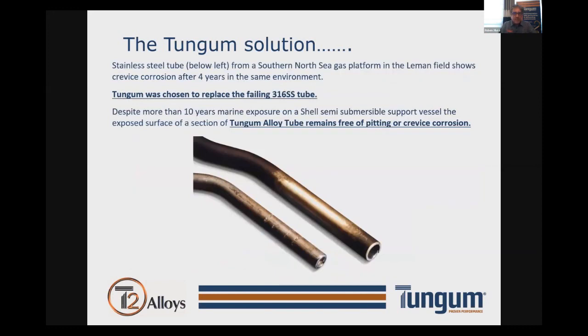So just as an example of the failures that have been experienced in the past, this is a typical crevice corrosion failure that you see. You can see my pointer circling the crevice area, and of course blotchiness of corrosion all along, in this particular case, 316 stainless steel. This very specific crevice was formed by the clamping that was used to hold the material in place. This is an offshore vessel that came from the North Sea area. And at the time that the user found this, they started looking for alternatives and they found Tungum.